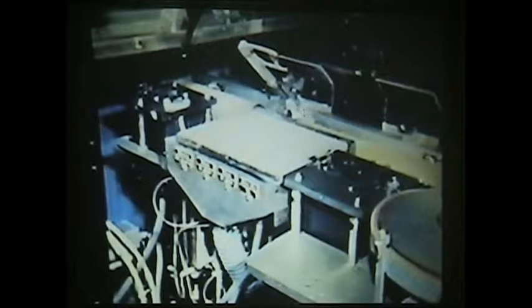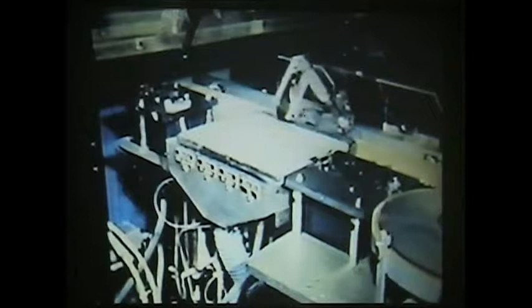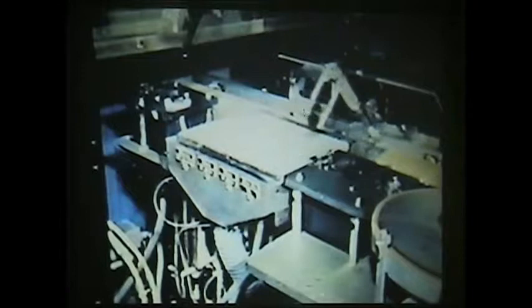then brings the wafer into the first tank, which is the development solution, to develop the photoresist pattern just exposed by the exposure sector. After the development, it goes into the fixing process, and after the fixing process, it goes into the washing, cleaning process. After the cleaning tank, the wafer is transported into the drying tank. Here we have two warm, clean nitrogen air knives to clean up the wafer.